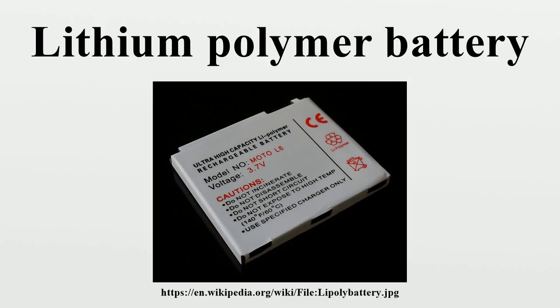All Li-ion cells expand at high levels of state of charge or overcharge, due to slight vaporization of the electrolyte. This may result in delamination, and thus bad contact of the internal layers of the cell, which in turn brings diminished reliability and overall cycle life of the cell. This is very noticeable for LiPos, which can visibly inflate due to lack of a hard case to contain their expansion. Compared to cylindrical Li-ion cells, LiPos lack integrated safety devices such as a current-interrupting device or a positive temperature coefficient material that is able to protect against an overcurrent or an overtemperature.